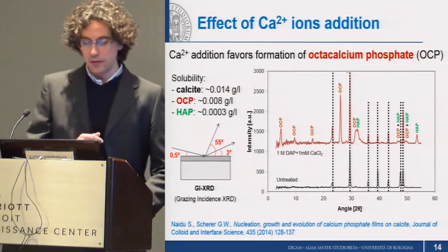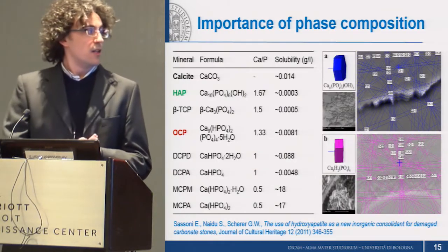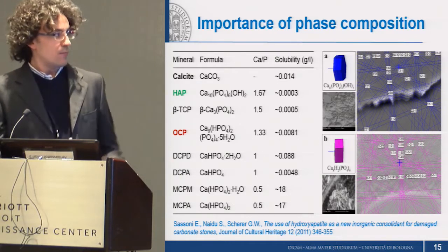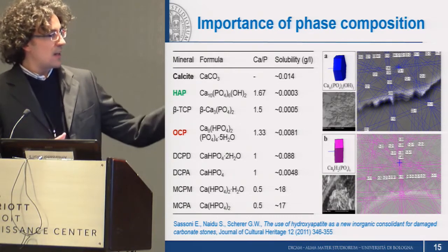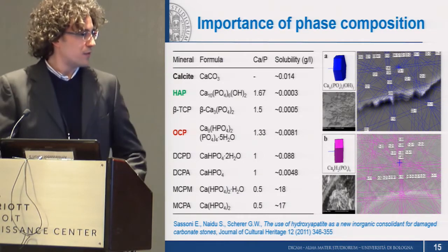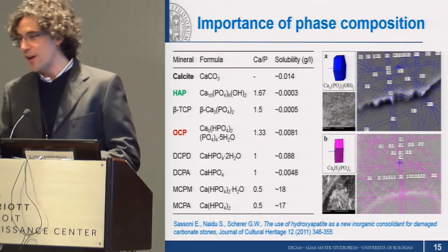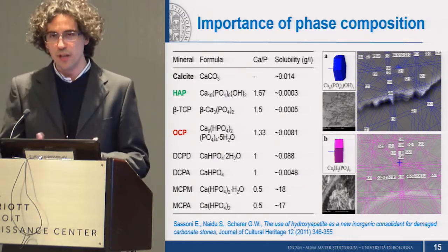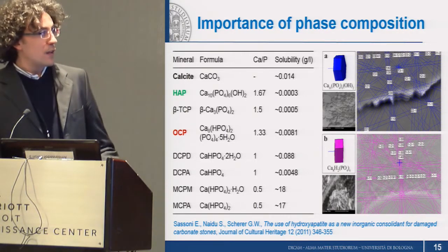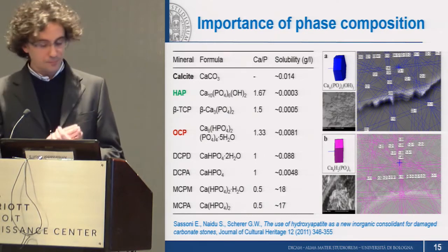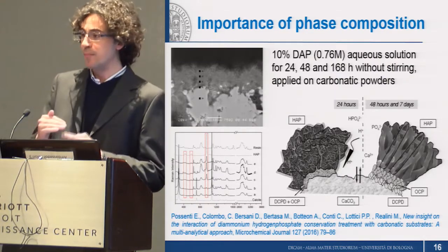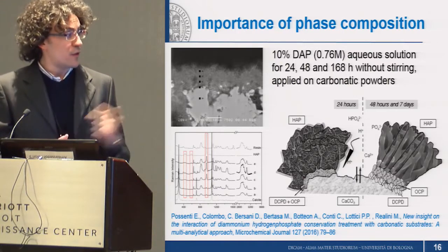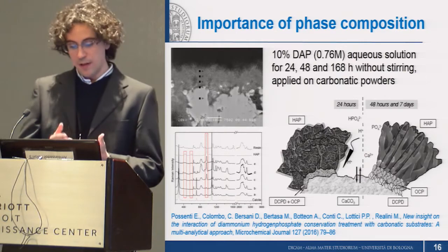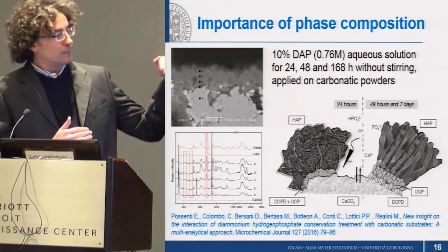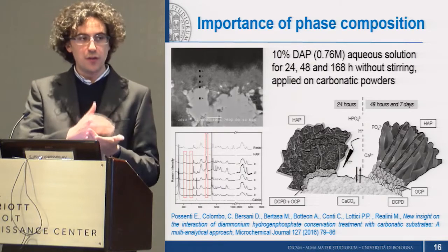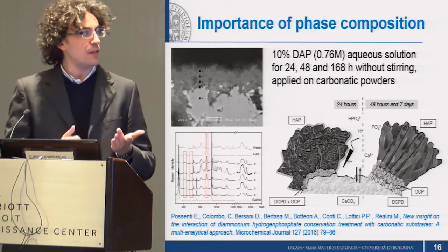But generally speaking, the nature of the phases that form is a very important and tricky point because, as you can see, half a dozen different phases may form, and in case very soluble phases form, such as monocalcium phosphate monohydrate, which has a solubility of 18 grams per liter, this would be useless for our purpose. So different groups, apart from ourselves, started investigating the effect of different treatment parameters on the nature of phases that form. For instance, some colleagues from Milan in Italy used micro-Raman to also try to identify, starting from the calcite surface, if there's a stratigraphy, a sequence of phases that form.